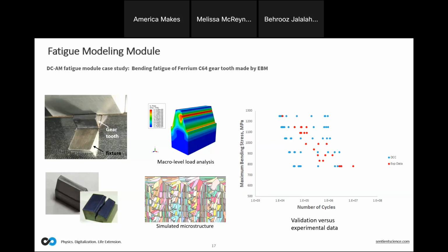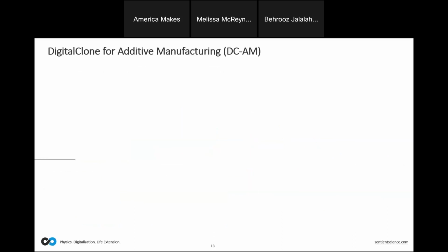Again, we did both the physical manufacturing and physical testing of this sample, and also the simulation. Here on the right-hand side, you can see that as we get to a more complex part, because of the more complex geometry, your microstructure is also going to be more affected. Because of that, compared to the previous one, even the experimental data now has a wider range. And again, that range falls inside the prediction that we are providing for this Ferrium C64, which is a high-strength, aerospace-grade steel. Go to the next one, please.